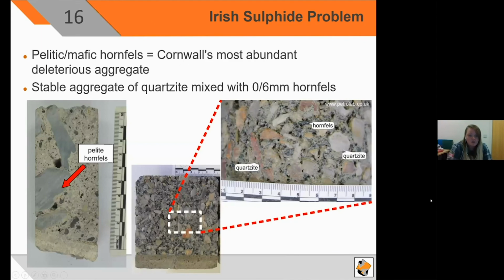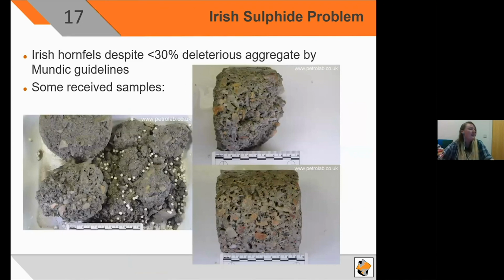So another slightly unusual aggregate for us, but you can still draw parallels from it. This is a typical pelite from Cornwall on the left. However, on the right, this is a usually stable red and white quartzite aggregate with no mica, but it has been mixed with a fine-grained 0 to 6mm hornfels, which is Cornwall's most abundant deleterious aggregate. So theoretically, from our Mundic guidelines, that equates to less than 30% of the deleterious aggregate, which would be stable. However, these are some of the conditions of the samples received. So you have ranging from intact and nice cores to literal debris.